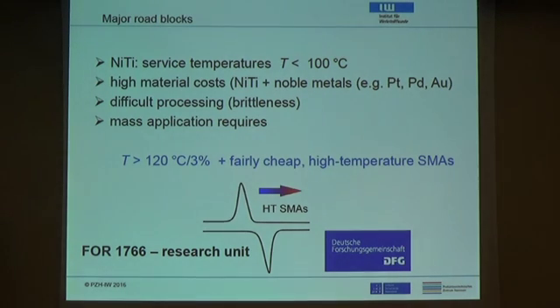The problem here is that standard nickel titanium doesn't work because it has phase transformation temperatures below 100 degrees C, which means that the service temperatures are also below 100 degrees C. One way to solve this problem is you take nickel titanium and then you add, say, platinum, palladium, or gold. The problem here is you need around 30% of these noble elements, which clearly drives up the cost quite a lot. You can avoid these elements by, say, adding hafnium, but then it becomes difficult to process the material.